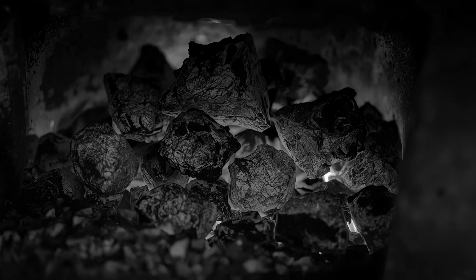Cold outside air was entering through that gap, flowing into the chimney through the crack, mixing with the exhaust gases, cooling them, increasing their density. The hotter the furnace burned, the more draft it created, the more cold air it pulled through that breach. A feedback loop. The furnace was drafting its own extinguishment. But even that wasn't the full answer, because cold air mixing with exhaust should still allow combustion. Inefficient, smoky, incomplete combustion, but not instant extinguishment.